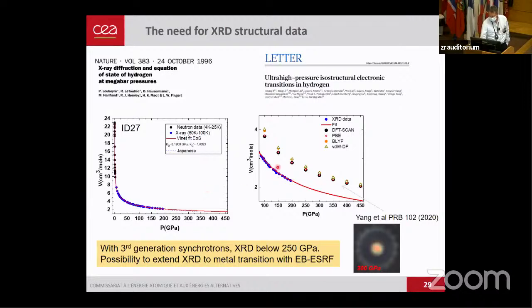But still, our measurements are a strong test of the ab initio calculation. So we really need third generation synchrotrons, as X-ray diffraction was limited to below 250 GPa. With the extremely bright beamline at ESRF, we have the possibility to extend this X-ray diffraction up to the metal transition, and this is one of our plans. Especially since at 300 GPa, 400 GPa, the sample is quite big. It's over 5 to 6 micron diameter.